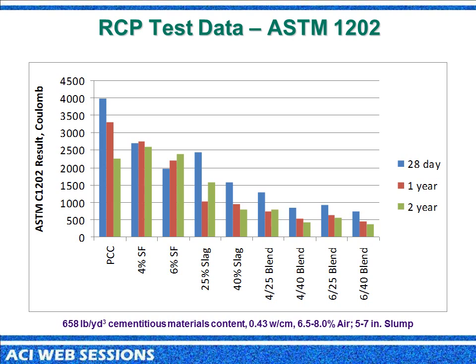We can see what we would see as a traditional trend, certainly by the use of SCMs. The Portland cement does see some decline. This is at 28 days, 1 year, and 2 year sets of data. But certainly we can see the benefits as we get further down into our blends, where we're seeing this blend at 4 and 40%, where we're seeing very, very low RCPs. However, this really doesn't give the full story.